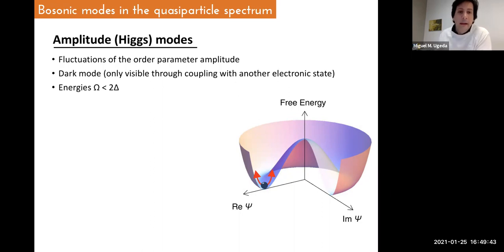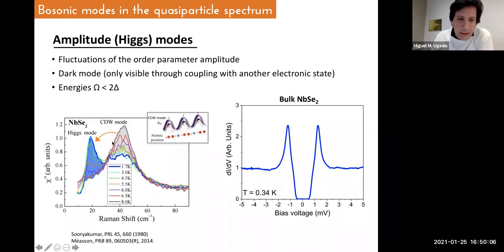They are not visible, and the only way to see them is through the coupling with another electronic state different from superconductivity. The binding energies of these modes would be quite similar to those of the features we have seen. But let me tell you that this has only been seen, to the best of my knowledge, in niobium diselenide in bulk.